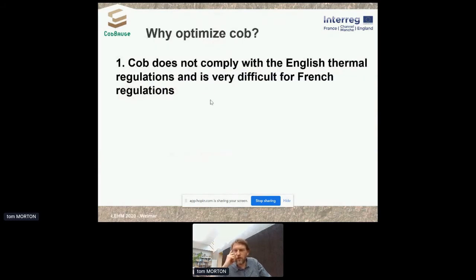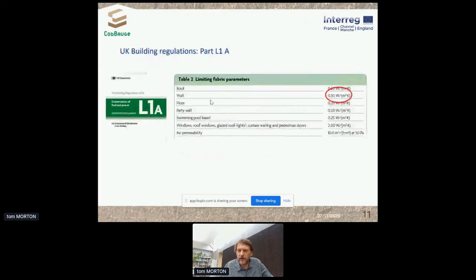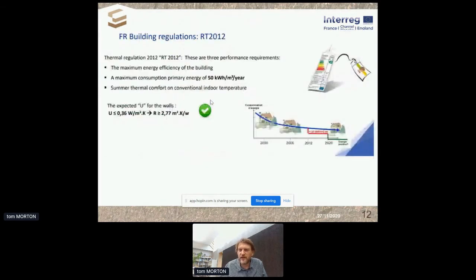So why optimize cob? There's several reasons. First, cob fails to comply with modern building regulations in France and in the UK. In the UK, there's a minimum requirement U value of thermal insulation of 0.3 watts per meter squared degree Kelvin, and in France, it's 0.36. And these are values which are only going to become more stringent as time goes on.